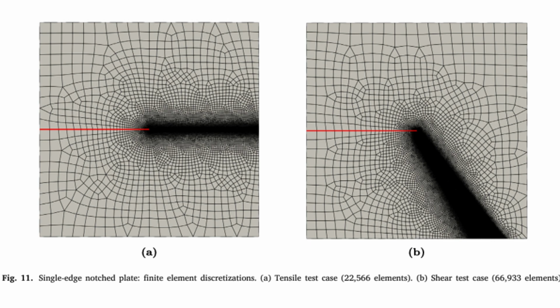The line search strategy you mentioned earlier. Exactly, the line search. But there's a complication specific to phase field models that makes standard line searches problematic. Oh, what's that? It's related to how these models ensure cracks don't heal themselves, which would be physically unrealistic. They use an internal history variable, often called mathcal-H. A history variable. What does that track? It essentially remembers the maximum amount of damage energy or strain energy density that each point in the material has ever experienced. The crack can only grow or stay the same based on this maximum past value.